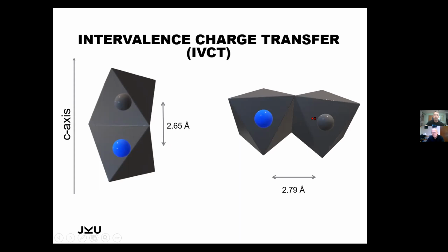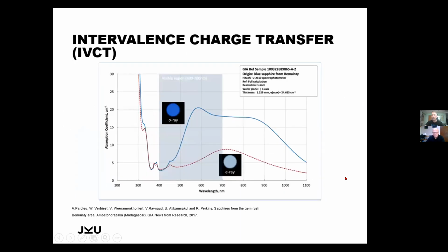So why is this important? Because if we look at the crystal of corundum, we have the C-axis, and along the C-axis we have this type of packing, whereas in the AB axis we have this type of packing. And this explains perfectly why we have a dichroic material. If we look along the C-axis, we will have the so-called ordinary ray, which is very, very color intense. And the extraordinary ray, which is in the AB direction, is typically much paler than the other one. In some cases, it can also have a completely different color.